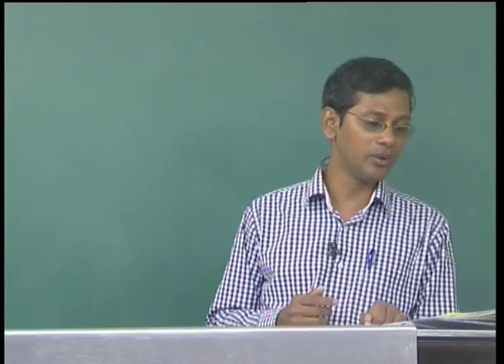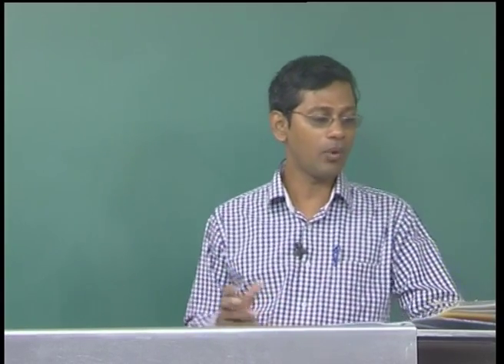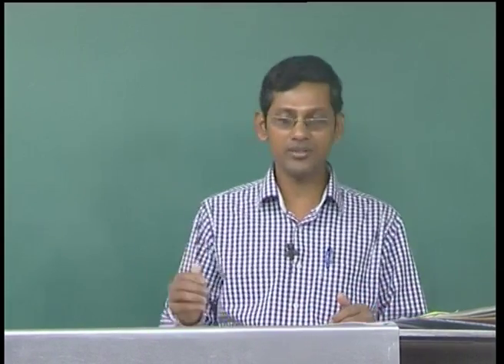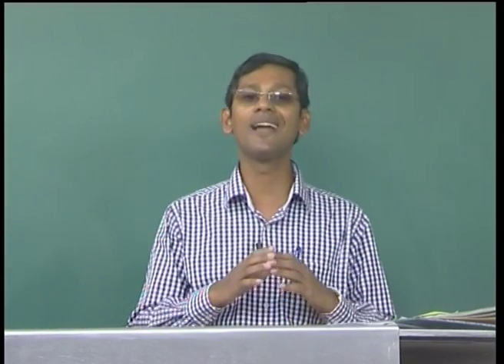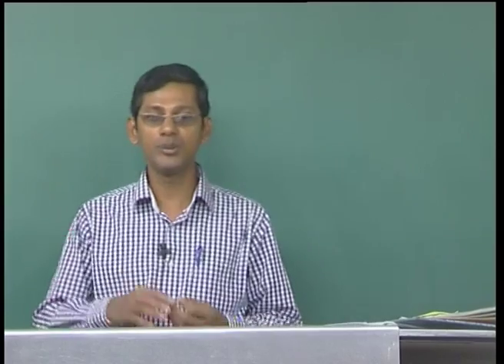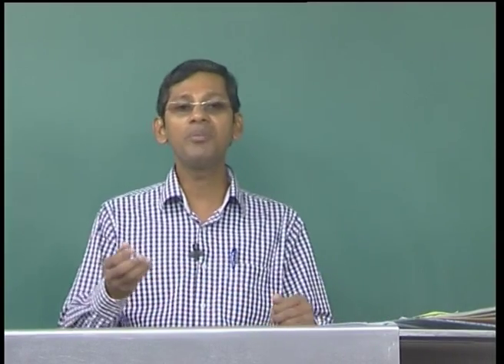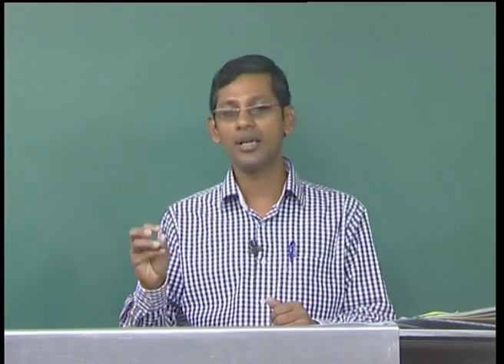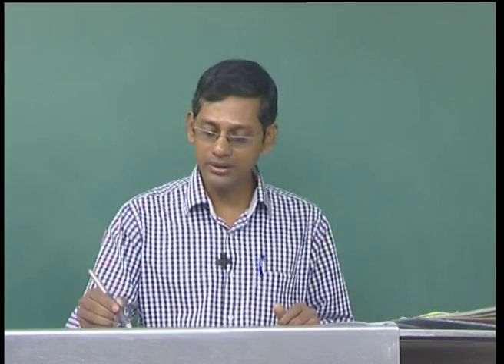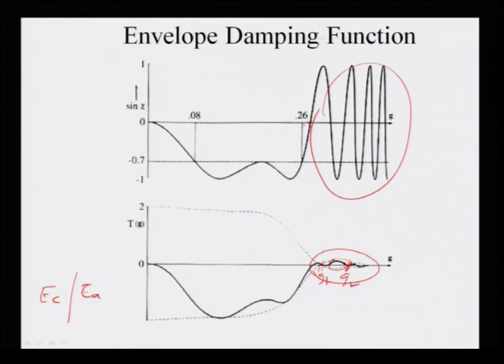Obviously, the first thing one can do, for example in the worst case of constant transfer function, is when the transfer is minimized. You start defocusing the objective lens in such a way that you do not see any contrast on the computer screen or on the fluorescent screen. If you do not see that, that becomes your starting point. From that you start changing the focus value and reach the Scherzer defocus value. This minimum value here, as you can see, corresponds to this number of sin psi, and this number happens to be 0.7.